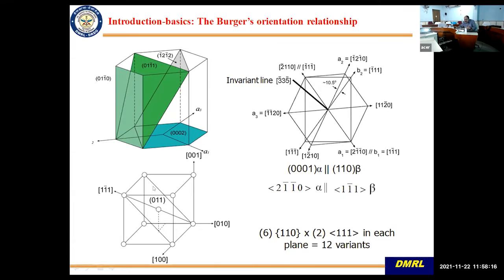So that is why whenever you look at the microstructures of titanium alloys, you will see a very geometric pattern. And this Burgers orientation relationship is the reason for that. In steels also you get these kinds of orientation relationships, like Kurdjumov-Sachs and others. So this is very important in titanium alloys. That is why I'm talking about it. And why we are talking about this is because mechanical properties are dependent on it. The microstructure affects the mechanical properties, okay, as you will see slowly.